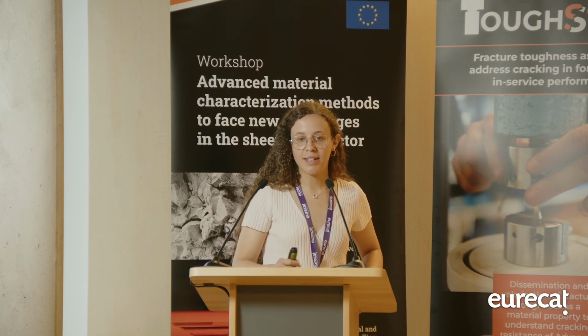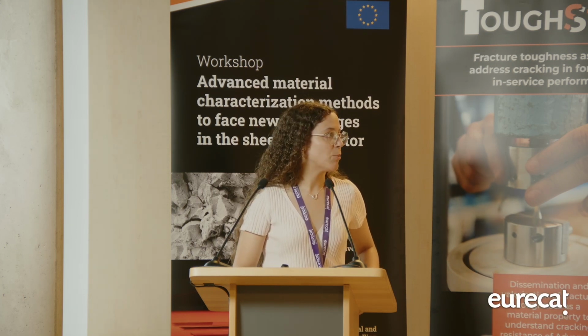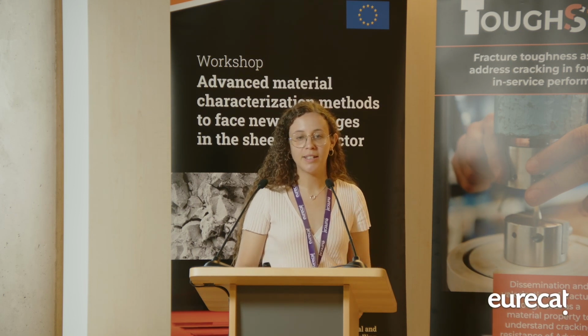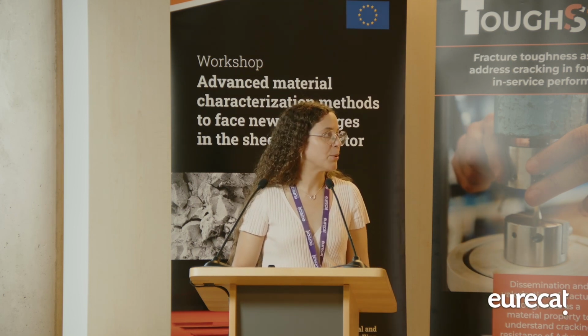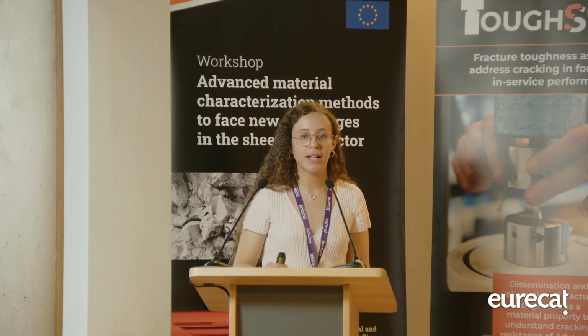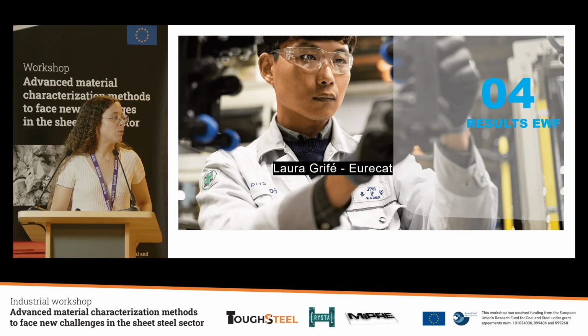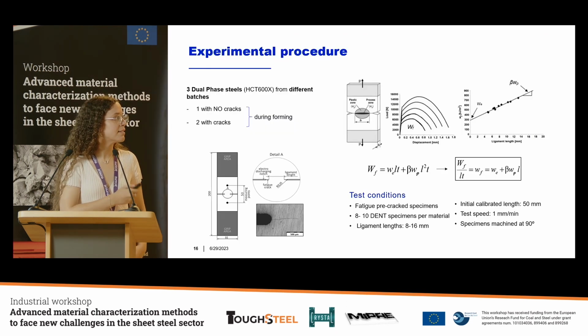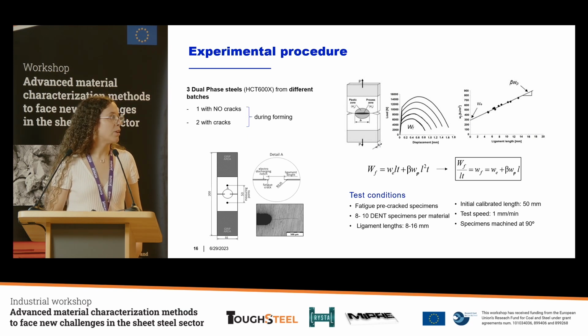So here for this case study, as Valerie already explained, they selected 3 DP steels with similar mechanical properties in all of them, only that they had problems. Two materials presented cracks during cold forming, and one was not presenting any cracks in this process. Then, as we were saying, we applied the essential work of fracture methodology. So let me just briefly introduce it.